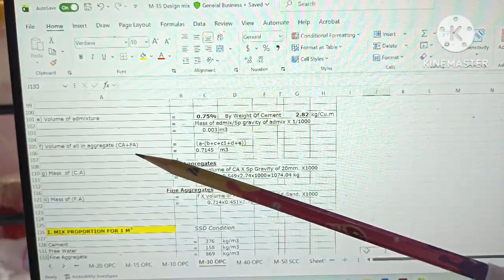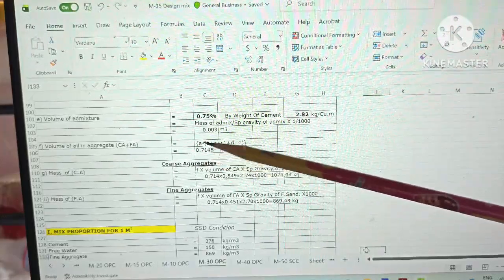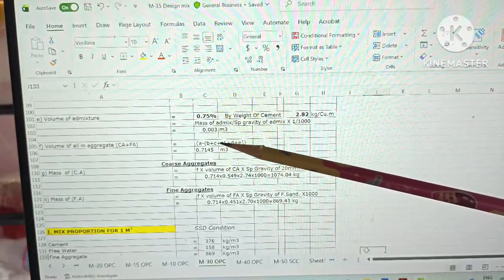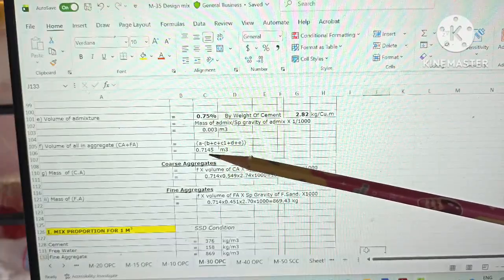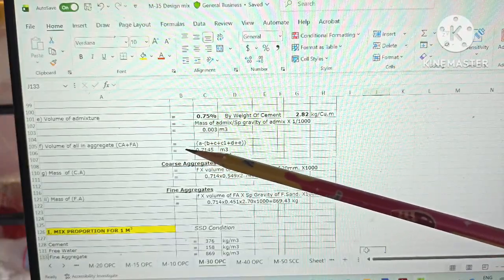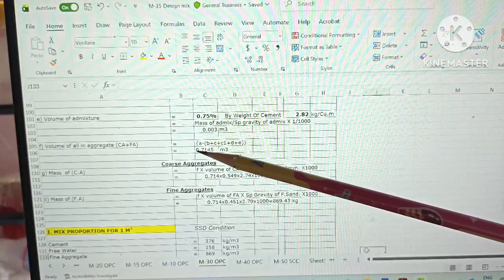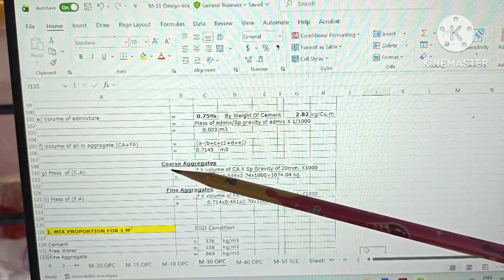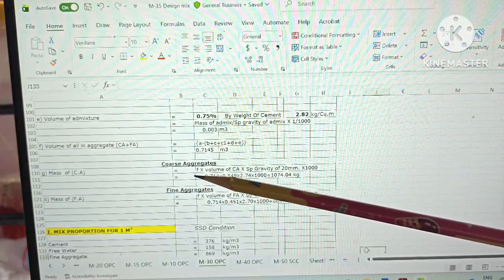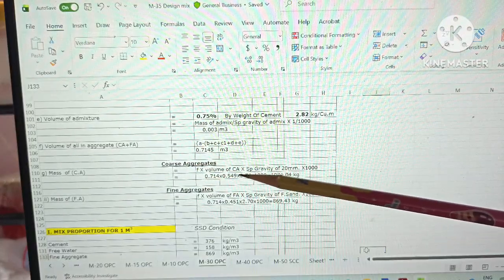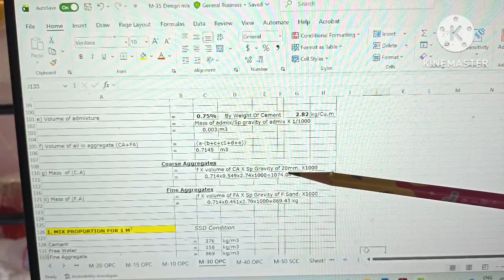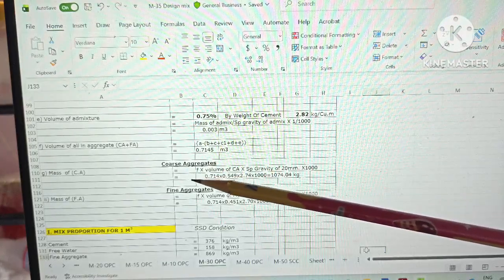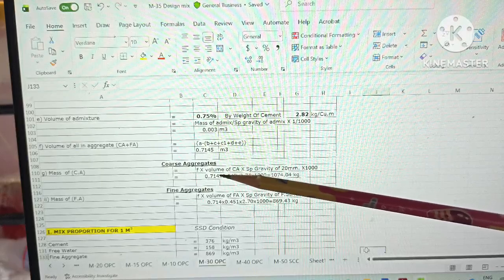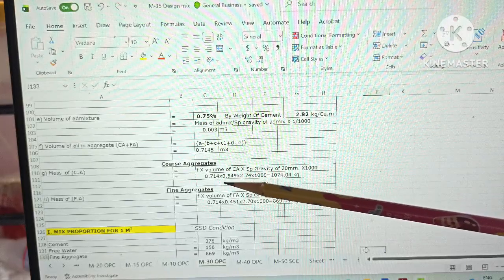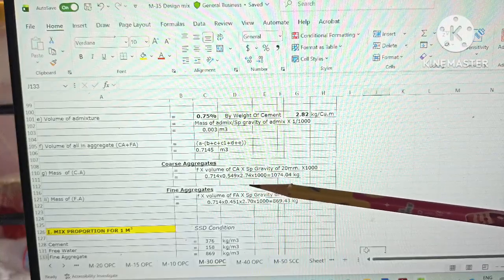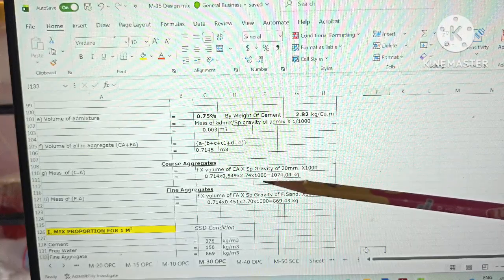Similarly, volume of all-in aggregate, that is coarse aggregate plus fine aggregate: 1 minus volume of cement, volume of water and volume of admixture, which gives you an answer of 0.7145 meter cube. Now this is the total volume of all-in aggregate, that is coarse aggregate and fine aggregate. But how much is the mass of coarse aggregate? To find the mass of coarse aggregate, the formula is F, that is volume of all-in aggregate, into volume of coarse aggregate, into specific gravity of coarse aggregate, that is 20 mm, into 1000. So F is already given, that is 0.715, and volume of coarse aggregate we have already found, that is 0.549, and specific gravity of 20 mm is 2.74, which is also given, into 1000, which gives you an answer of